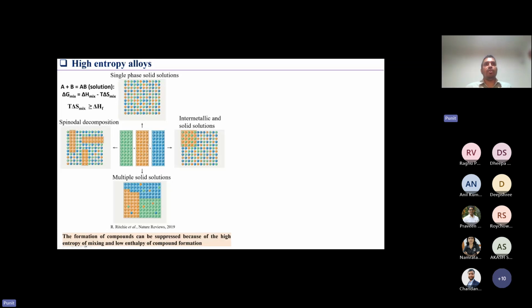For example, you can end up with this intermetallic and solid solution, or you can have multiple solid solutions. There is a possibility of a spinodal decomposition also, but you can also end up with a single phase solid solution. This essentially happens when the enthalpy of formation of the compound, delta H formation, is lower than the configurational entropy that you increase by mixing multiple principal elements in large amounts.